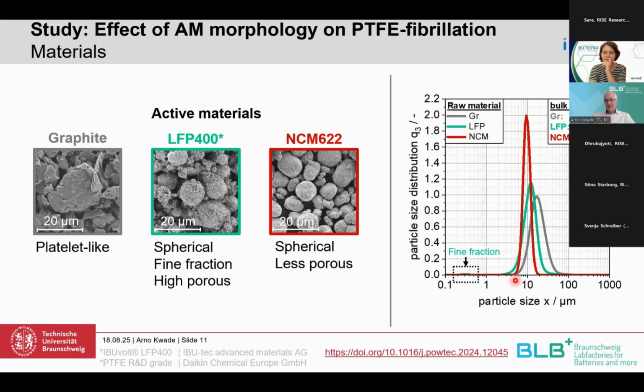Here you can see the particle size distribution. So the NCM has the closest and smallest particle size, although the most narrow particle size distribution. And there is then some LFP. You see it's a polydispersive LFP. There are some primary particles, seems to be. And we have the graphite, which is the widest and coarsest material.